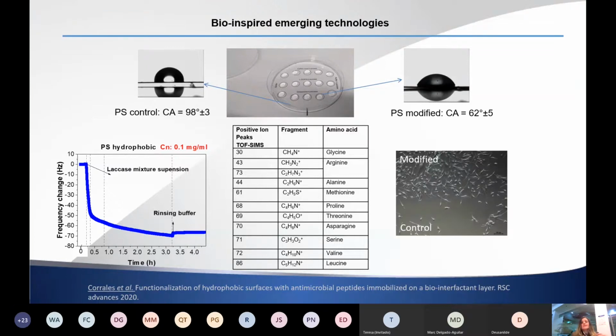And we saw that it's a suitable treatment for replacing plasma, because as it's irreversibly absorbed on the surface, we tested many solutions, such as bases and acids. We saw that the enzyme was still on the surface, and we use this as a replacement, for example, for treating polystyrene plates, the Petri dish, for helping to grow cells.